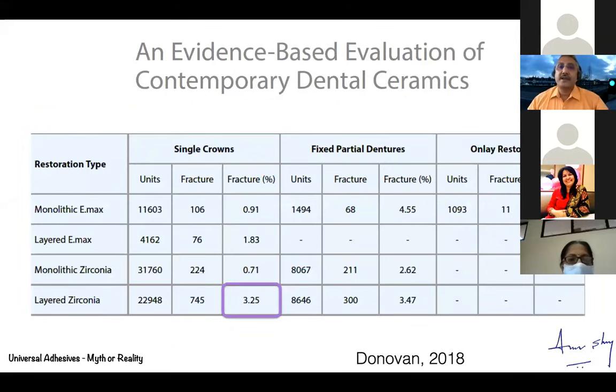But for FPDs, the highest fracture rate is here for monolithic Emax. So Emax is not really good for bridges. It is extremely good for single units, especially in the anterior, and the aesthetics is superb with layered Emax. And if you see for layered Emax single units, the fracture percentage is just 1.83, and for monolithic, it is only 0.91. So if I am going to use the right material, then I will get the right results.